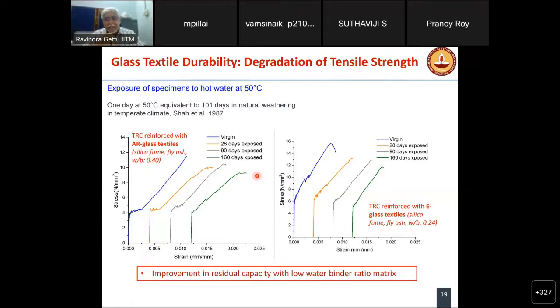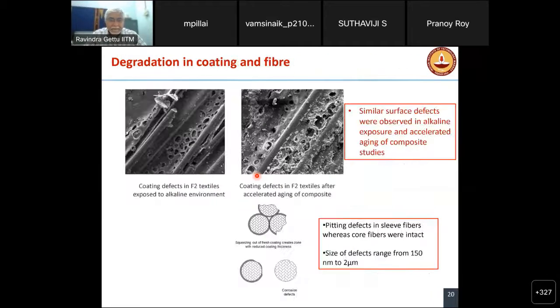Then the durability comes in. We want to protect the glass textile so that there is no attack because of the binder. And this we can look at in different ways. We have done some microstructure studies where we are looking at the defects in the coating which promote the attack. So a lot of times we see that the coating, even instead of being uniform, has some defects, and the alkaline solution penetrates and attacks.